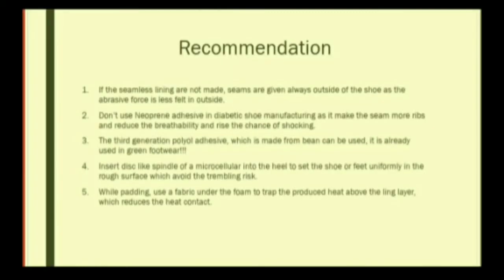What are the recommendations? If seamless lining is not made, seams should always be placed on the outside of the shoes so that the abrasive force is felt outside. Do not use neoprene adhesive in diabetic shoe manufacturing, as it makes seams more rigid and reduces breathability, raising the chance of chafing. The third-generation polyol adhesive made from beans can be used instead, and it is also used in green footwear. Insert disc-like spindle or microcellular material into the heel to set the shoe uniformly on rough surfaces, which avoids the risk of stumbling.